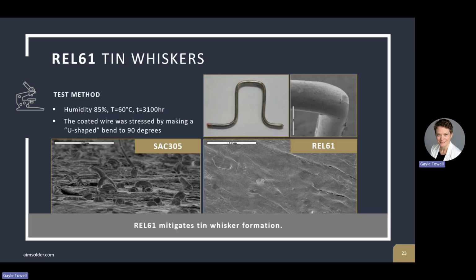Some people are concerned about tin whisker growth, the growth of these little tin whiskers off the surface. And we performed a tin whisker test under conditions of 85% humidity at 60 Celsius for 3,100 hours. And what we see is that SAC305 shows tin whisker growth under these conditions, whereas REL61 does not. So REL61 appears to mitigate tin whisker formation.